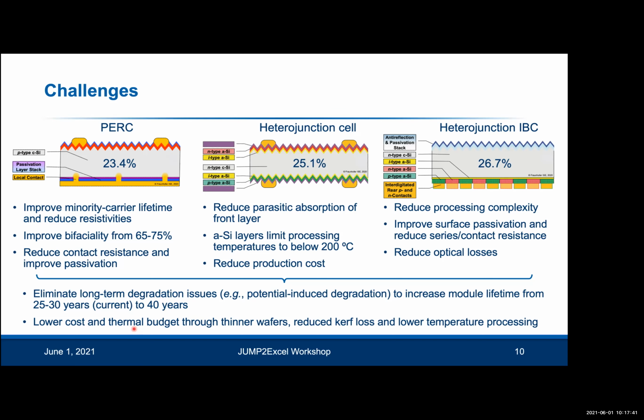And also another common challenge is to lower the cost of production, for example, by having thinner wafers so that from each ball of single crystal silicon you can cut more devices, as well as having reduced materials loss when you're slicing wafers from a ball of silicon. And also to reduce the processing temperature in order to decrease the carbon footprint of manufacturing silicon photovoltaics. So that was a summary of the silicon PV roadmap.